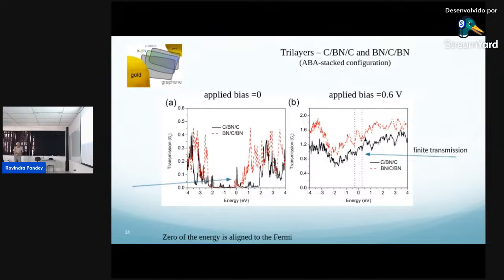With 0 bias for this particular case, the black is basically the graphene-dominated system. You have a small peak, transmission occurs, and this will be current. For the boron nitride case, which is red, you can see it is flat, showing a gap with no transmission around Fermi. So at 0 bias, these heterostructures behave like what we expect. Once we turn on the bias, you can see here, this is our applied window, we have finite transmission. It doesn't matter what the material is, it's going to be a metal-like heterostructure. So either monolayer or trilayer, they simply behave like ohmic contacts. The ohmic current is coming out from those heterostructures, although there is a gap in one case and zero gap in the other.